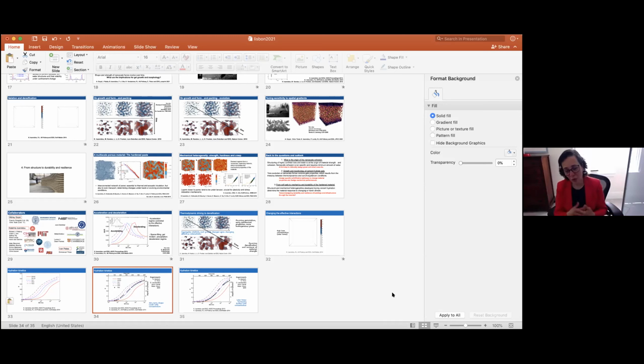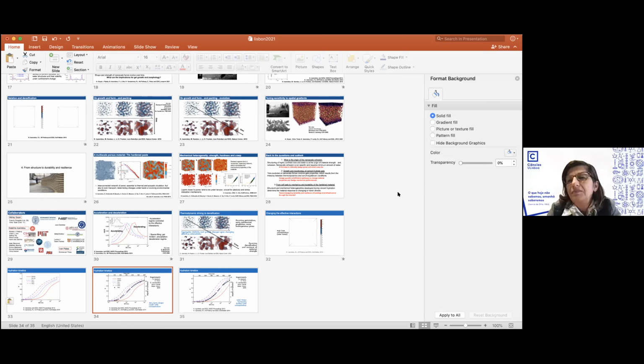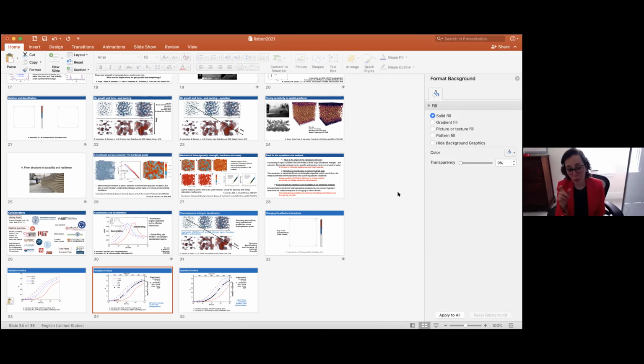And we have done it qualitatively, just to make nice movies for us, but it's very tricky to understand how to, because in the simulation, of course, you can do it in many different ways, and how do you choose things in a way that makes sense. So one strategy we have identified is this: now that we know how the type of interactions are evolving, depending on the ionic composition, we can go back to data that from the experiments have monitored the evolution of the ionic composition, and then understand what could be a realistic way for which this can evolve.